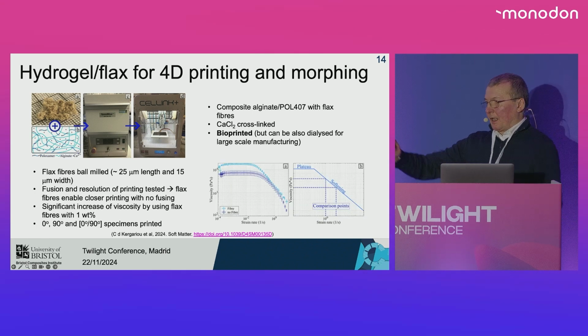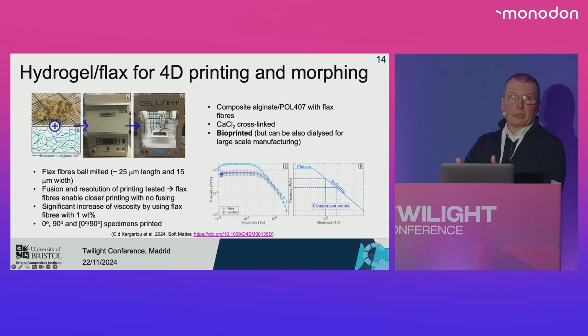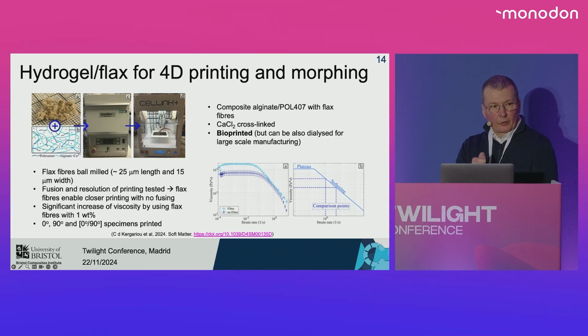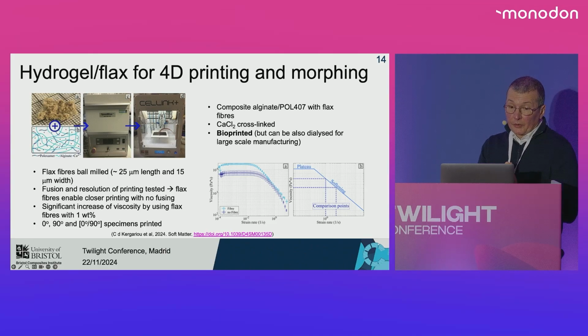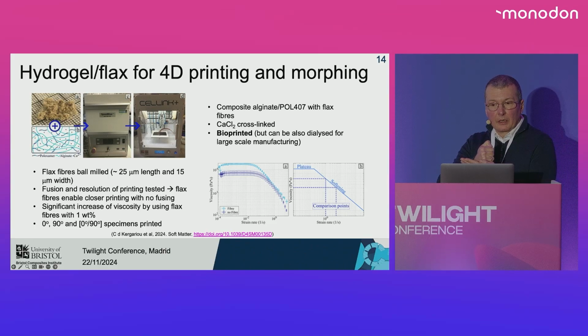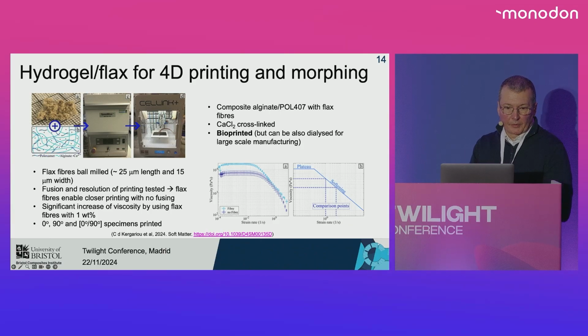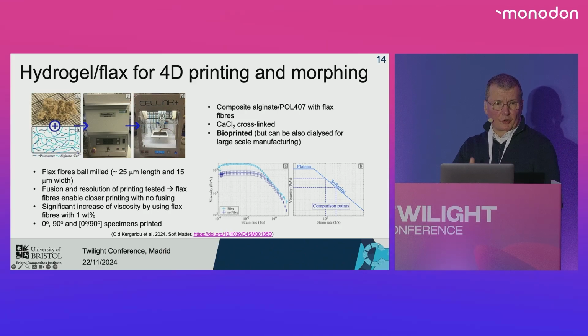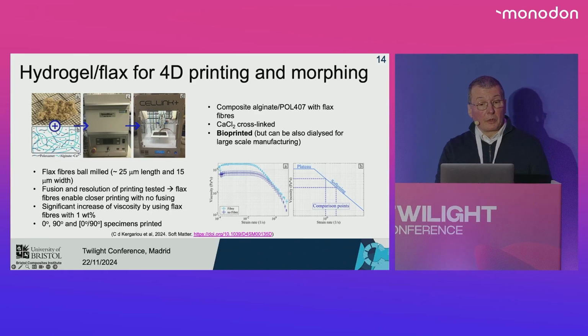And the fibers are not long fibers that are embedded within the hydrogels. We ball mill, so the dimension of these short fibers is between 25 microns and 15 microns of width. We have tested fusion resolution during printing, and what we have noticed is that the flax fibers enable really close printing, like really sort of reinforced filaments that you would use in 3D printers with thermoplastic materials, and there is no particular fusing that we have observed, which is good for bioprinting and for the resolution of really high-quality structures. The flax also contributes to increase the viscosity,